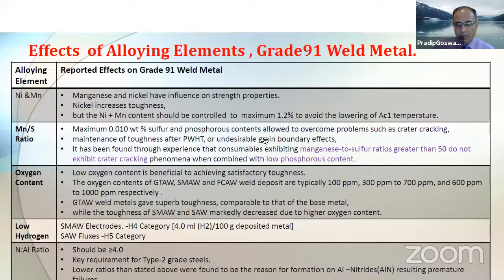Manganese to sulfur ratio. Typically, a manganese to sulfur ratio greater than 50 does not exhibit the crater cracking phenomenon, combined with low phosphorus content. So the manganese to sulfur ratio basically is needed. Manganese is an element which generally binds with sulfur to form manganese sulfide. And in one way it helps to keep the steel clean and keeps the tramp elements under control.